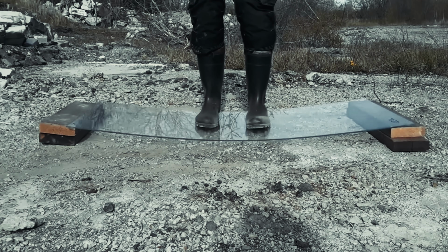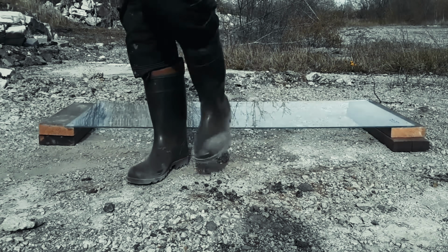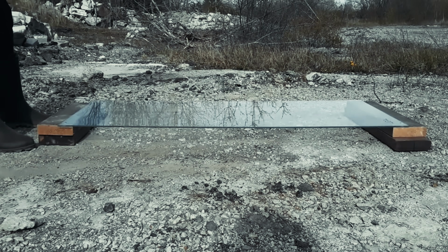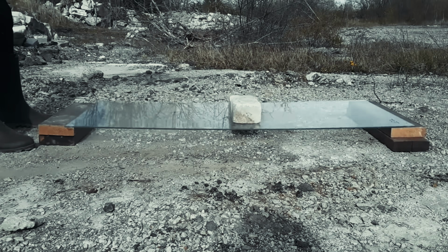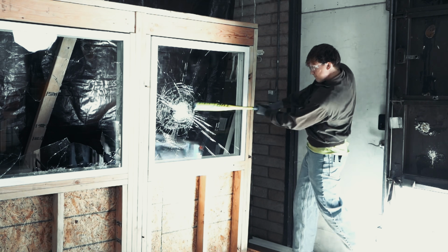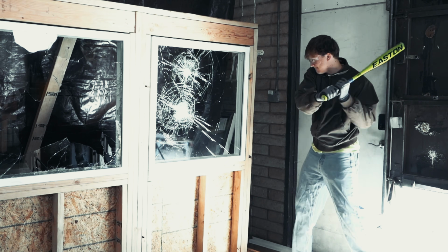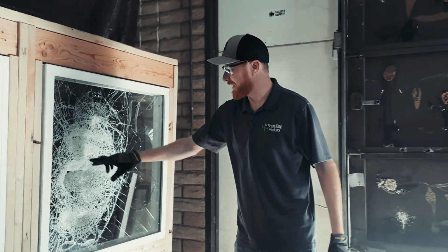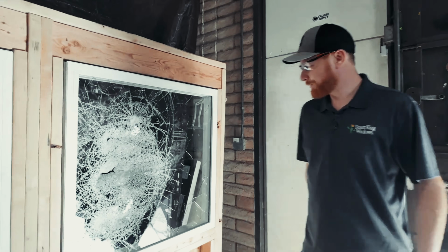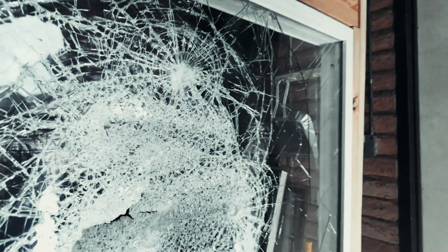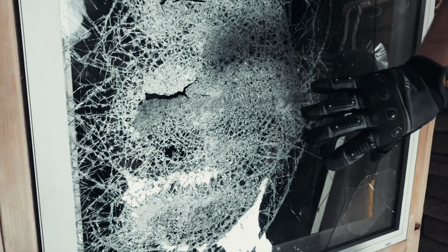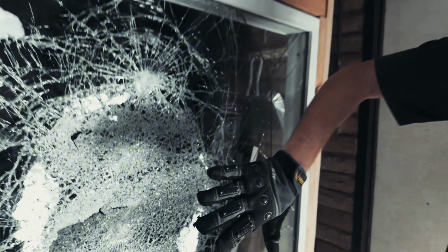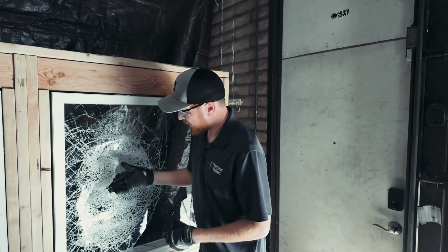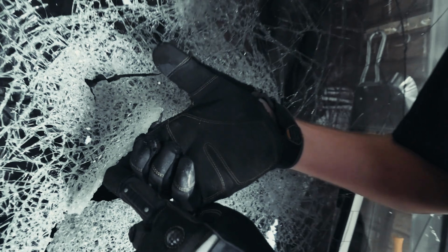To break through the compressed outer layer requires roughly 4 to 5 times more force than ordinary glass of the same thickness. But when tempered glass does break, when that compression is finally overcome, the stored energy releases all at once. The entire pane shatters simultaneously into thousands of small, blunt fragments rather than sharp shards. That's not a flaw, it's the whole point. It's engineered to fail safely.